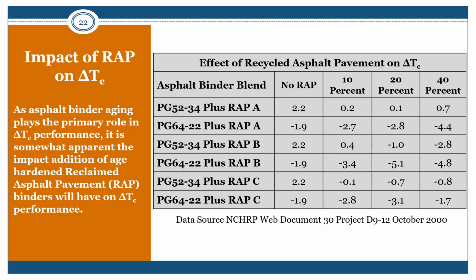This table shows that addition of recovered RAP binders to virgin PG 52-34 and PG 64-22 produce either decreasing positive values or more negative delta Tc values with increasing RAP contents. The primary thing to note from this figure is that as the binders age, the positive delta Tcs decrease or become negative, or more M-controlled. For example, the PG 52-34 binder plus RAP B goes from an S-controlled delta Tc of 2.2 to an M-controlled with more addition of RAP.